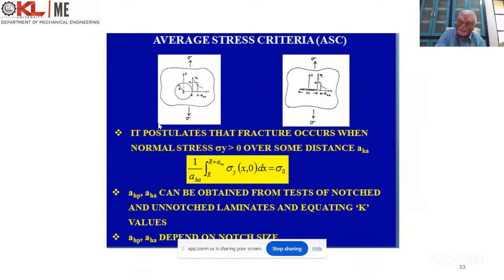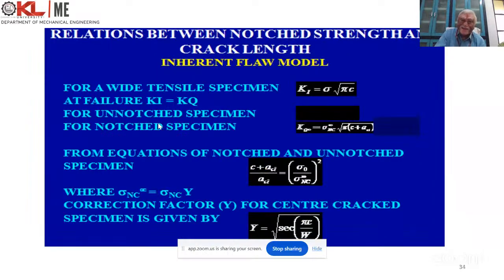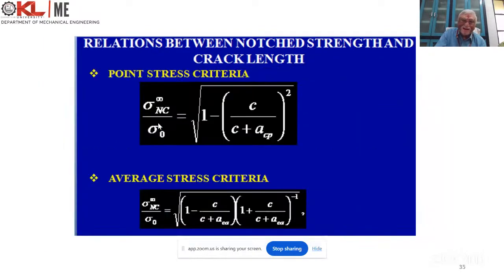This is the average stress criterion. When the stress is varying in a non-linear fashion, why not take the average of that and see whether the average stress exceeds the strength of the material or not. All three are equally good when we examine different composite materials, so you can select any one of them and use it. These are all ways of relating the fracture strength to the crack size with a fictitious or characteristic length ahead of the crack.